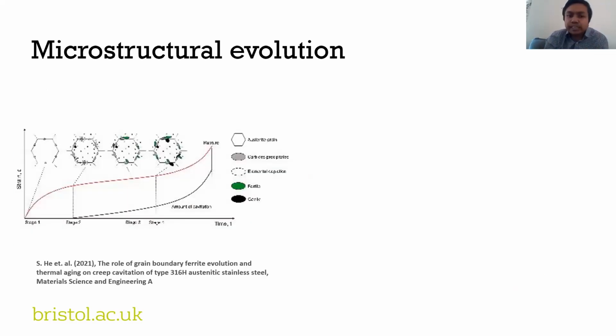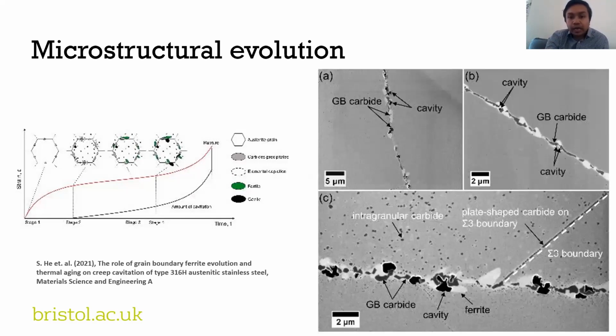And we use other techniques, for example, advanced microstructure based techniques in cooperation with the Interface Analysis Center at Bristol, where we can track the different stages of evolution of microstructure during the creep deformation, how it is evolving for different types of loading, different types of constraint. For example, we can use weld materials. We can look at all sorts of different materials, and this is another way to combine with our crystal plasticity model to get the certainty that what the model is predicting is actually a true representation of the deformation and damage occurring in the material.